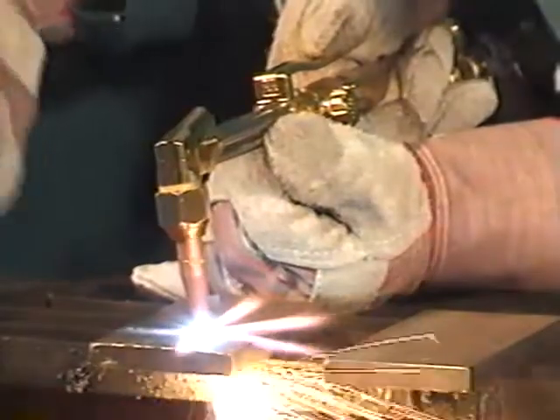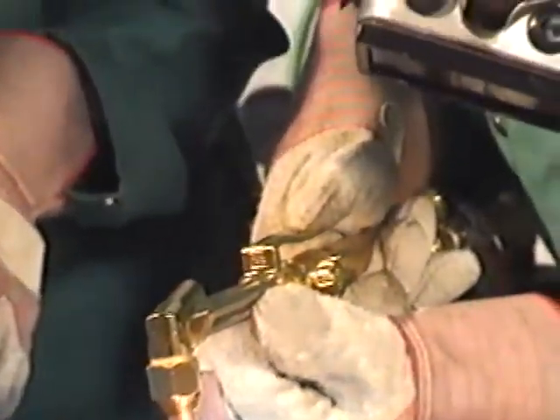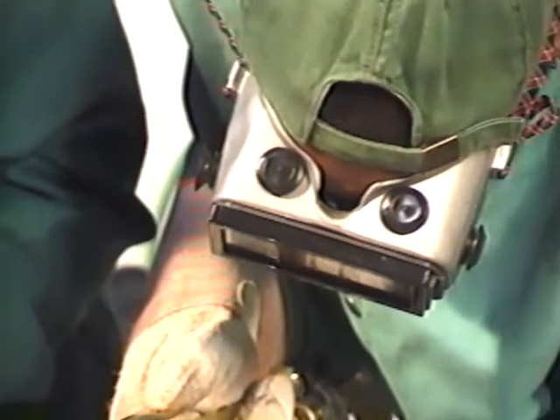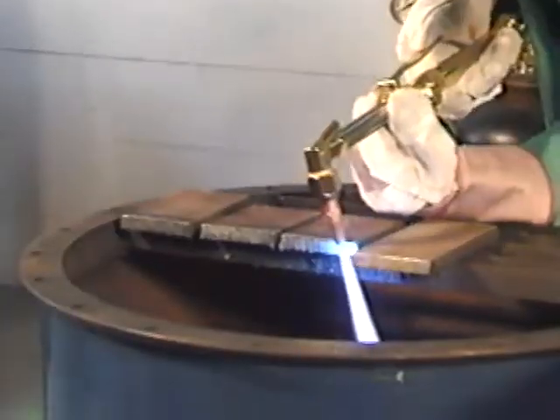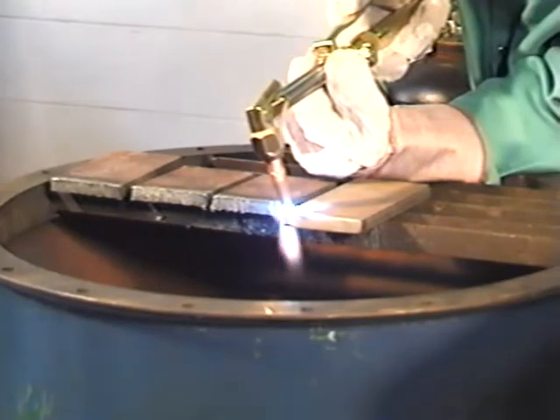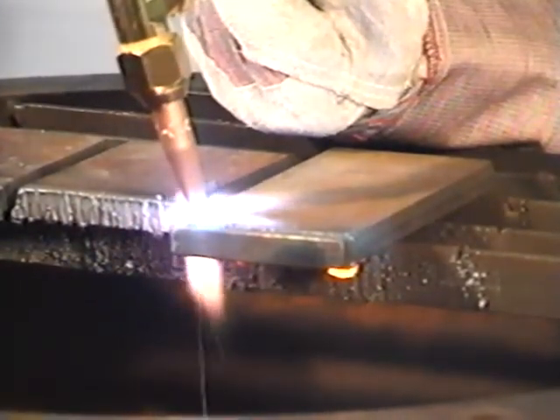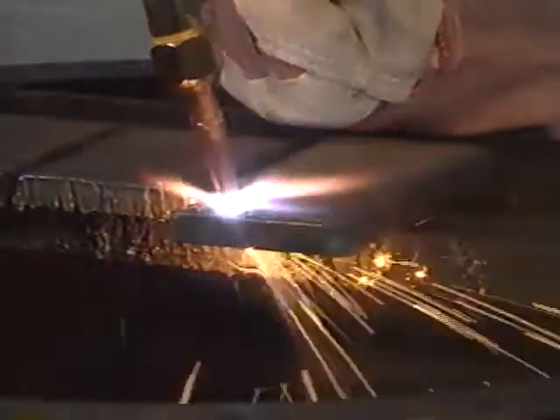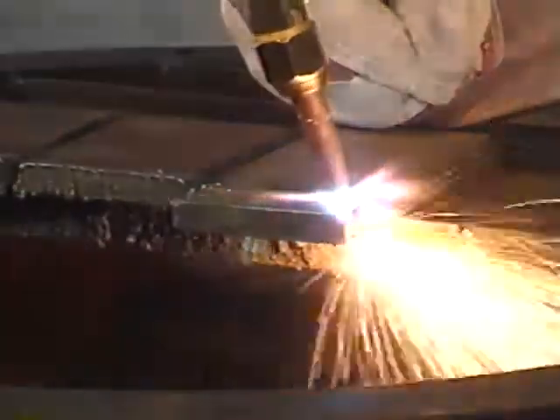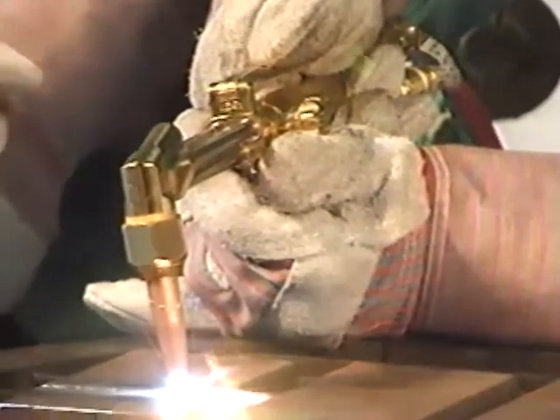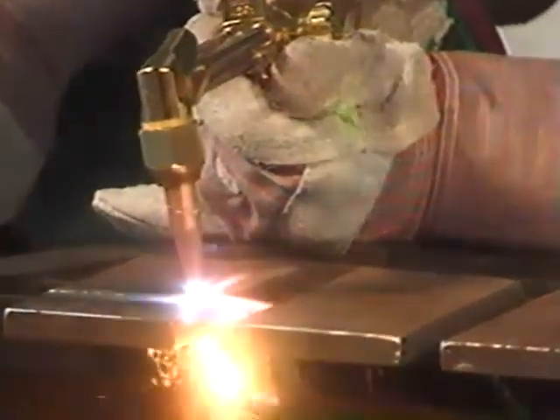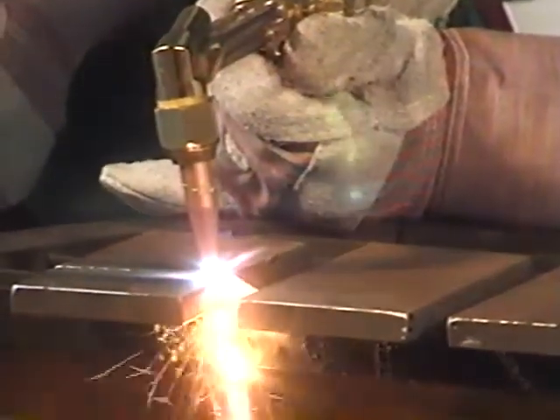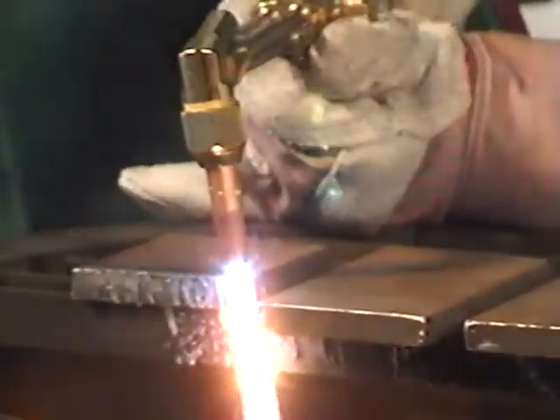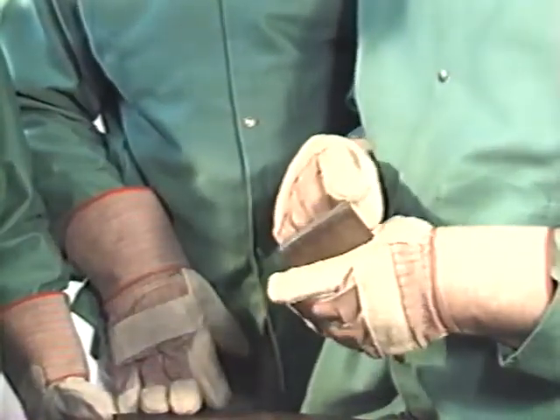A well-made cut in metal has clean edges and minimal slag or waste metal. The cut is called a kerf. The correct position for cutting freehand in metal is a two-hand grip. Slide the torch along with one hand while stabilizing it with the other. The tip should be held at a 15 to 20 degree angle. When the metal is preheated to approximately 1500 degrees, it will appear bright red or orange. Then apply the cutting lever. The oxygen flow will produce a clean, even cut. This is an example of a clean cut made in steel plate with an oxyfuel cutting outfit.